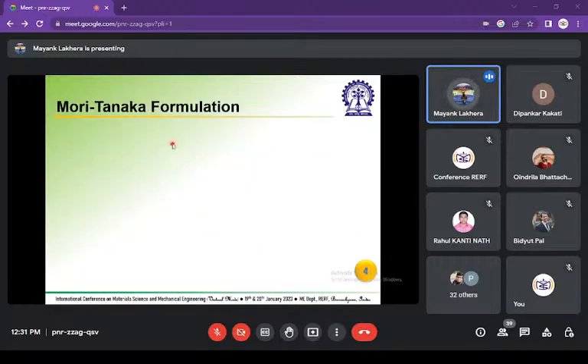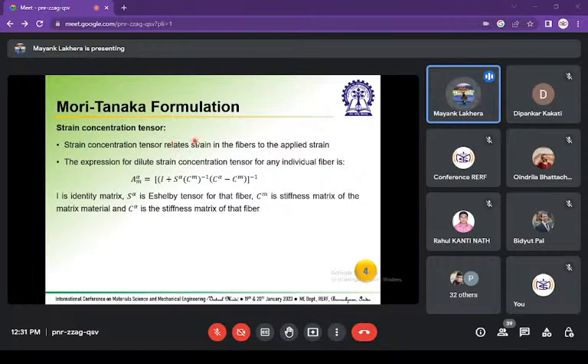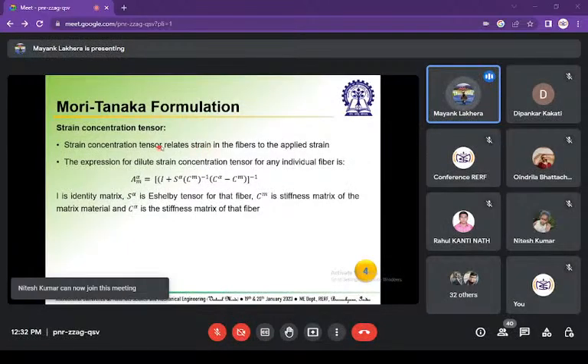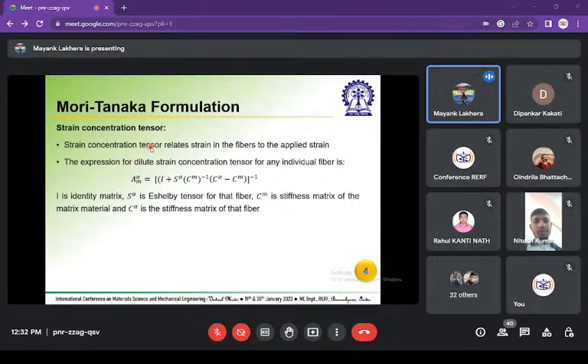For the Mori-Tanaka formulation, the Eshelby tensor was applicable when there is a single inclusion in a matrix. But as you know, one fiber also affects the properties of the other fibers. So let's say there is some stress in one fiber, that stress will also affect the stress in the other fiber. Mori-Tanaka was the first to relate these stresses and strains in the individual fiber and also to the overall fibers. The strain concentration tensor basically relates the strain in some.